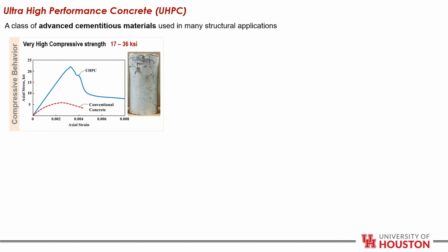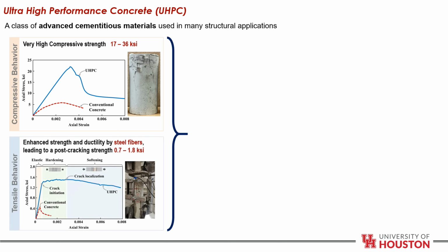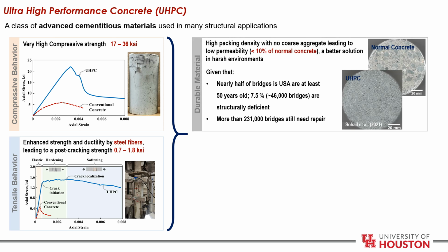So, UHPC is a new class of cementitious material that has been used in many structural applications. UHPC is characterized by its very high compressive strength, surpassing normal concrete by more than 5 times, and it has a very enhanced tensile behavior, given that fibers work in bridging the cracks and increasing the post-cracking strength, allowing more ductile response.